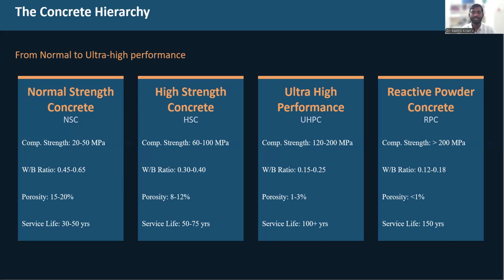Some literature has reported even 600 megapascals of strength, particularly the compressive strength in the reactive powder concrete. And all of it is because of the material composition, the water binder ratio, and the reduction of porosity in the reactive powder concrete. So this is typically the concrete hierarchy.